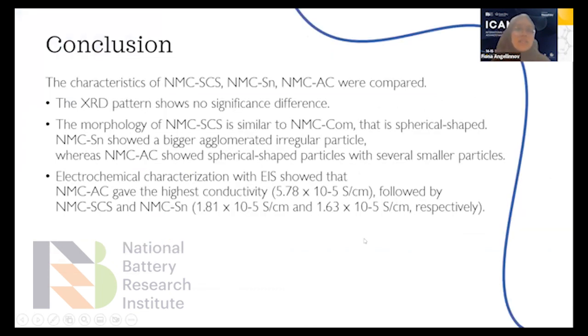So we can conclude that the characteristics of NMC-SCS, NMC SN, and NMC AC were compared. The XRD pattern shows no significant difference. The morphology of NMC-SCS is similar to NMC commercial, that is spherical shape, and NMC SN showed a bigger agglomerated irregular particle, whereas NMC AC showed spherical shaped particles with several smaller particles. And for the electrochemical characterization, it showed that NMC AC gave the highest conductivity compared to NMC-SCS and NMC SN.